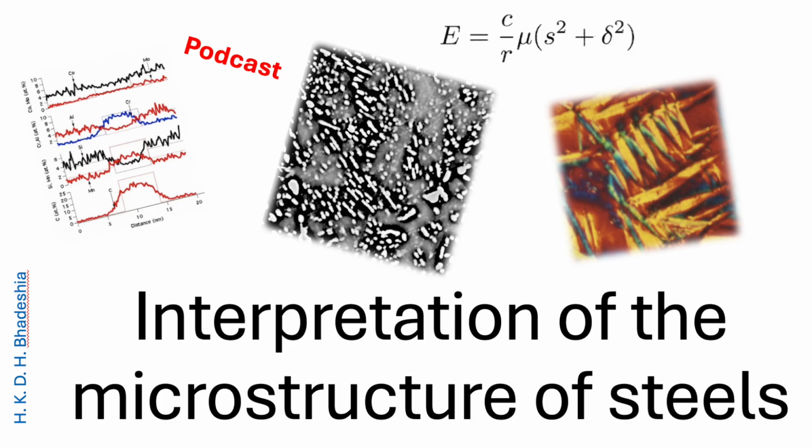If you see a phase, like a colony of pearlite, growing across or enveloping a prior austenite grain boundary, you know instantly it was a diffusion-controlled reconstructive process. It's a dead giveaway. It's the gold standard. Secondary visual cues help too. Bainite etches relatively dark because it's a dense mix of ferrite and cementite, lots of interfaces for the etch to attack. Untempered martensite, which lacks these precipitates, often etches light.